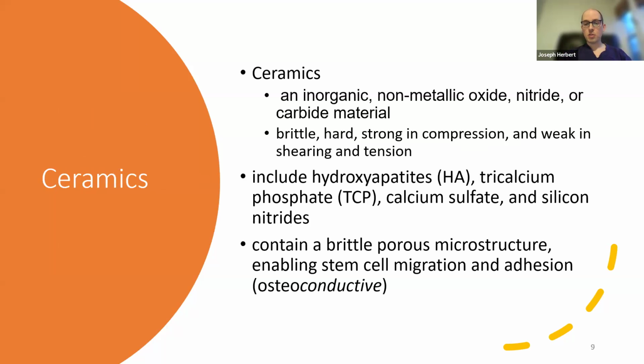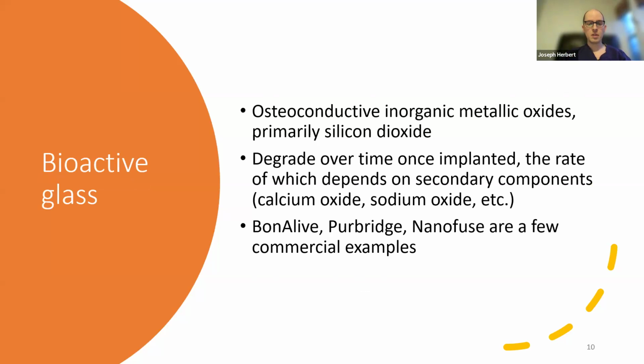Ceramics, just in general, are an inorganic, non-metallic oxide, nitride, or carbide material. These can typically have characteristics of being very brittle, very hard. They tend to be very strong in compression, but weak in shearing and tension. These include hydroxyapatite ceramics, tricalcium phosphate, calcium sulfate, and silicon nitrides. These typically contain a brittle porous microstructure, and that actually enables stem cell migration and adhesion. So this is an example of something that's osteoconductive, that's also inorganic.